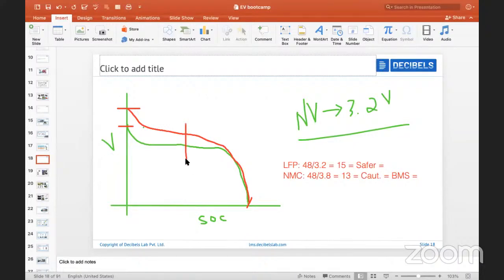If you take a BMS, you see the curve is very flat for LFP. It's a millivolt of difference per SOC change. For 1% of SOC, you may have a millivolt of voltage change. I believe you're able to follow me. But here, for every percentage of SOC drop, you can see a significant difference in the voltage of the cell. So the complexity of building a BMS for LFP is greater compared to NMC.